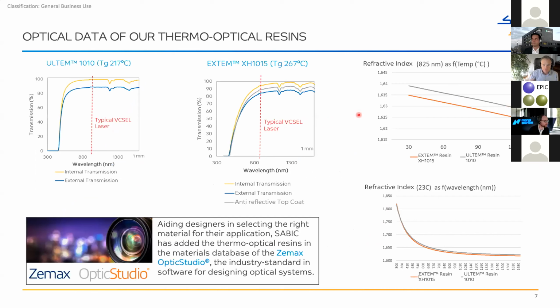This is quite a busy slide. I think it's more for your reference if you want to take a look at it later. The refractive index of Extem is relatively high compared to glass, 1.63 at near infrared wavelengths. Of course, there is a dependency on temperature. So the dn/dT of any plastic is always a disadvantage versus glass. The slope of plastics is roughly one order higher than glass. But optical designers can work with that.